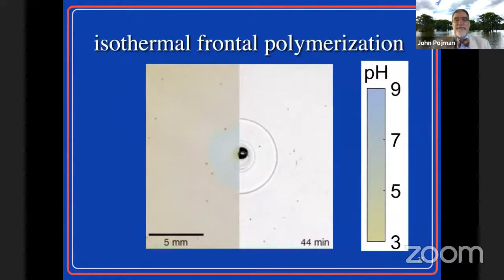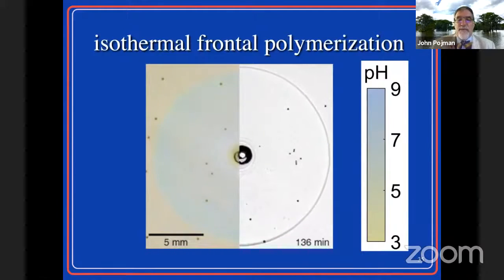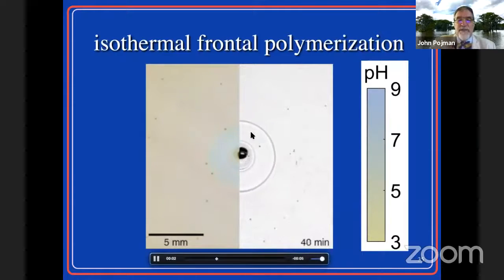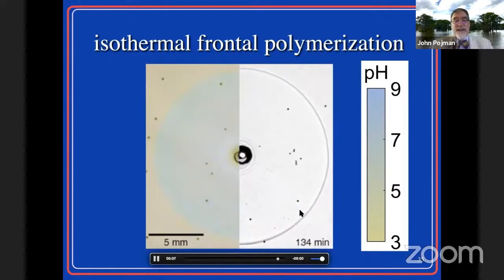It's also possible to get a propagating front. This is a movie that is sped up. What's happening is a split view. On the left is a pH indicator system. So we started out a system at low pH, add a little bit of base. The reaction causes the production of ammonia, which diffuses, causes fast reaction. And you get a reaction that propagates with a constant velocity. This is showing that simultaneously, we're having a conversion of monomers into polymer. So this is an exciting process.